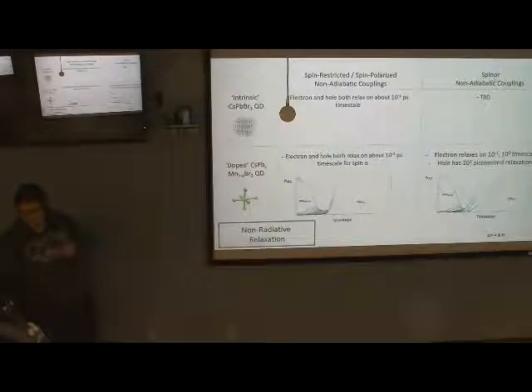But for the spinors, with non-adiabatic couplings, or if you include spin orbit coupling, you see the population of HOMO minus 20, which is in the perovskite band again, ideally. So it decays, you see some quick relaxation from the perovskite bands. They're a little slower. If you look closely at the time steps, there's not much of a difference here.